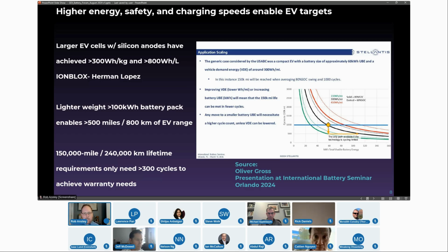So really, cycle life, although it has become this obsession with 1,000 cycles, what Stellantis was saying is, wait a second, if we make a really efficient car and a really high energy density cell, cycle life becomes far less necessary. So for example, we make a 600-mile vehicle, which is sort of the battle between Tesla and Lucid right now. Let's say one of them gets to 600 miles. To hit the warranty, they need 300 cycles. That's it, 300 cycles to hit their warranty and to last for over a decade. So it sort of puts this obsession with 800 to 1,000 cycles